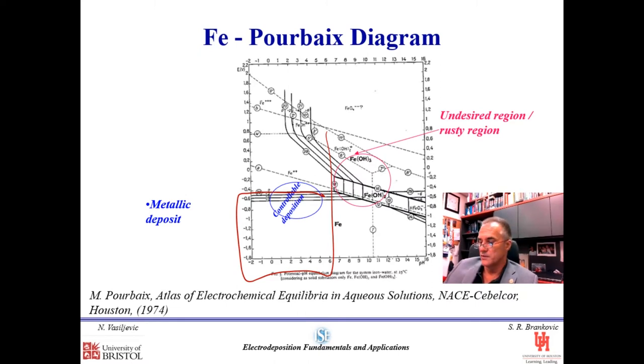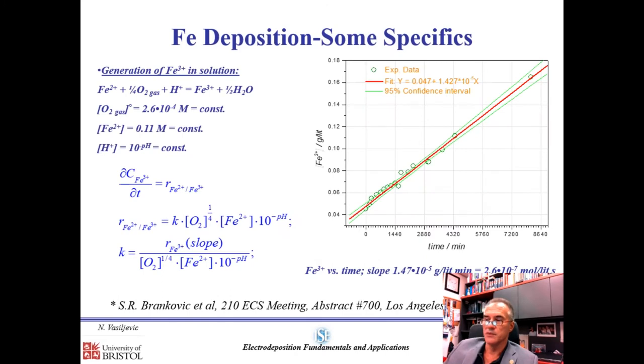Another important thing is that iron 2 ions, which are a common source for iron electrodeposition, are oxidized by dissolved oxygen from the air, which at normal pressure is about 2.6 times 10 to the minus 4 molar concentration in the solution. For that reason, this oxygen will oxidize iron 2 into iron 3.